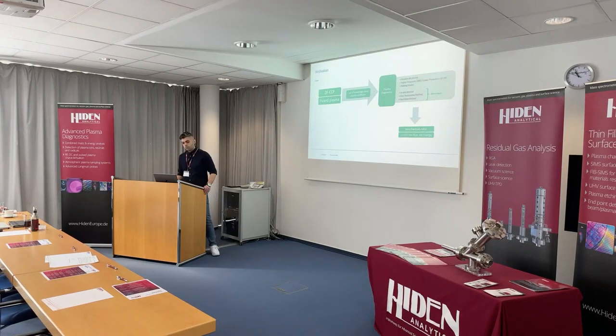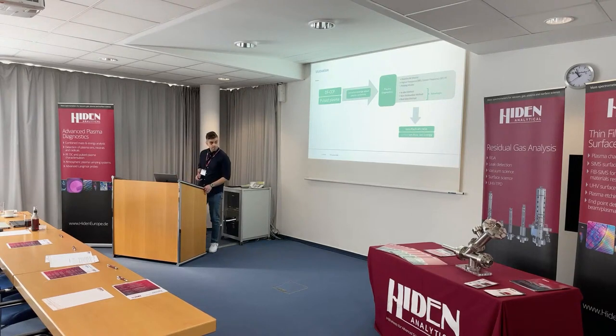Here there are two ways that can help in this regard, dual frequency CCP and pulsed plasma. And because of the lack of knowledge about the plasma condition, I did plasma diagnostic. I start with argon plasma because it's simple and it doesn't degrade the tool itself. And I did some higher frequency and lower frequency variations, and I did experiments on pulsed plasma mode. The advantages are it's an in situ, non-destructive and real-time method. And it gives us insight on ion per radical ratio and control over ion flux and ion energy.